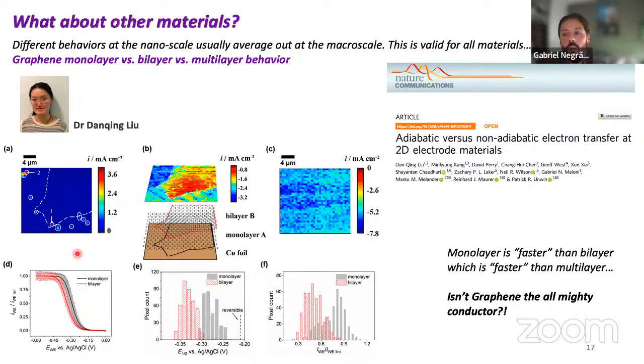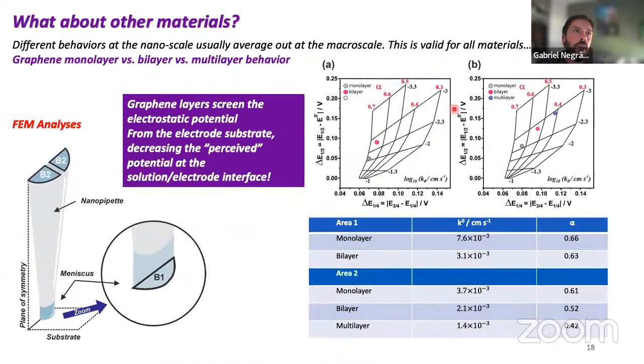And we couldn't understand exactly why, since graphene should be this amazing conductor. It's just like a sheet of graphene on top of water. We're talking about going from one atom to two atoms on top of water. And we can characterize how many atoms by many techniques, including Raman. And how to explain that? How to explain, for instance, that monolayers are faster than bilayers, which are faster than the multilayers? So we resort, again, to the same kind of simulation, the same kind of working curve to recover values of K0s. And we did recover, and we can see that monolayers are quite a bit faster than bilayers, which are quite a bit faster than multilayers. So we can now quantify, and we try to explain why that is.